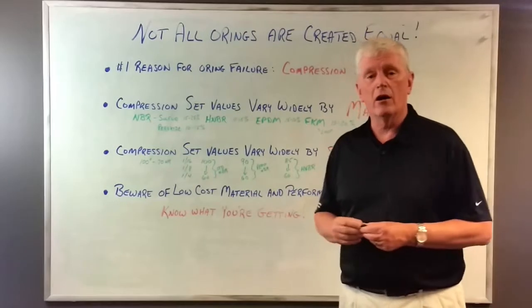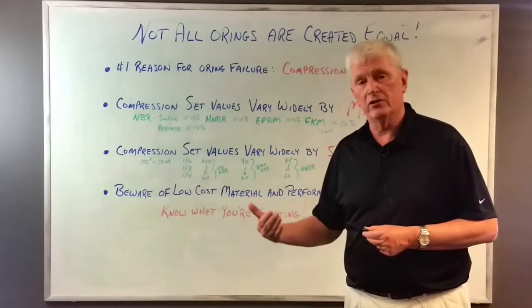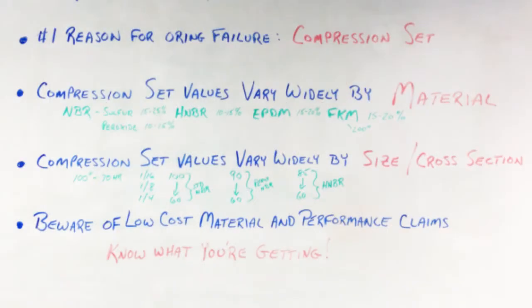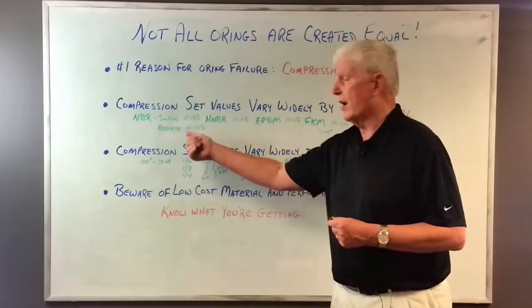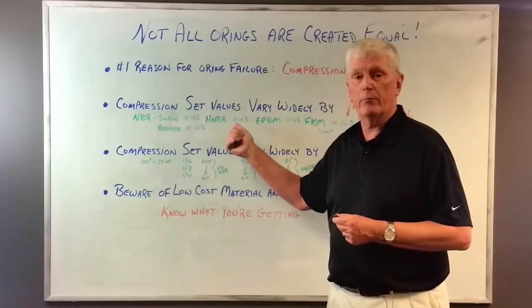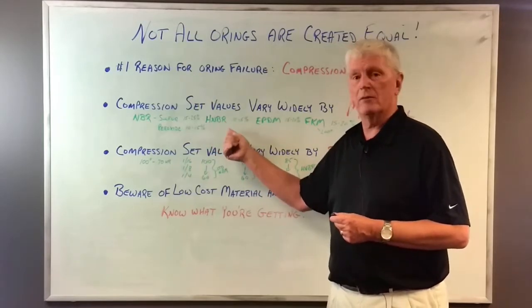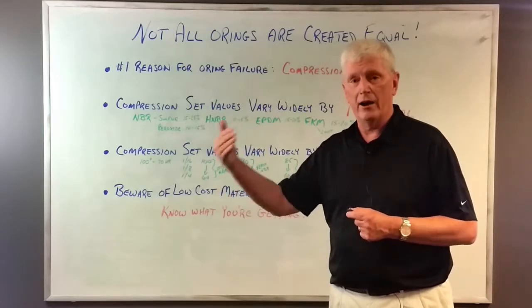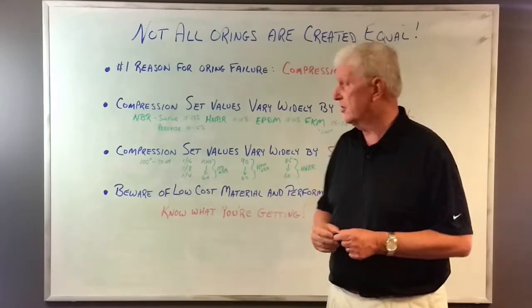Significant improvement for a lot of face seals for both static as well as dynamic applications. You go to an HNBR, which is considered an upgrade in the NBR family, you'll see very similar compression set characteristics to the peroxide cure. If compression set is all that we're dealing with, peroxide cure might be an alternative because there's also a premium on price to go to the HNBR. Now, another reason to go to the HNBR would be for higher temps and for other application concerns.